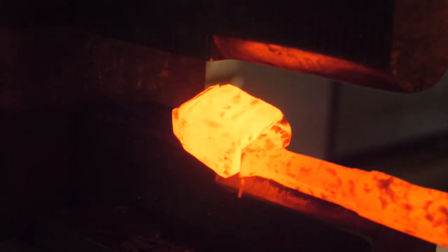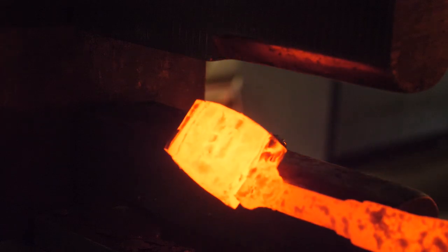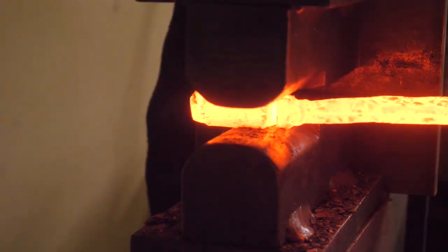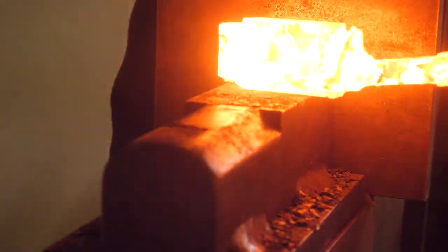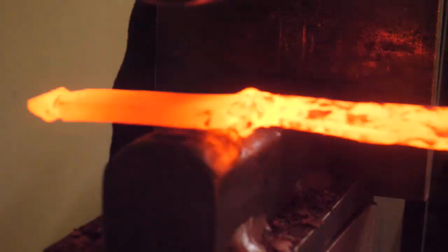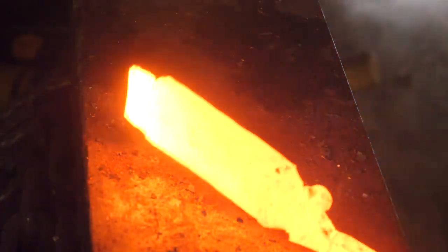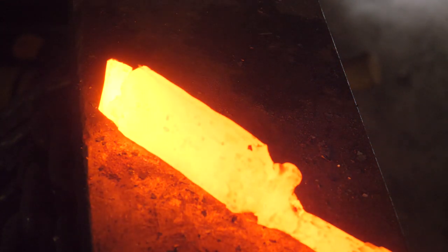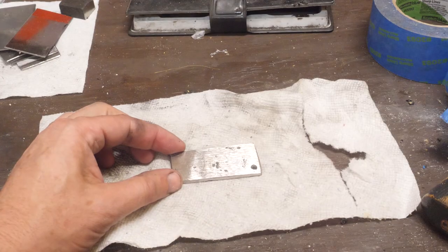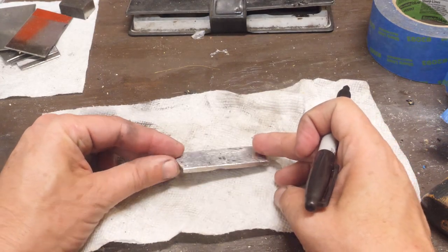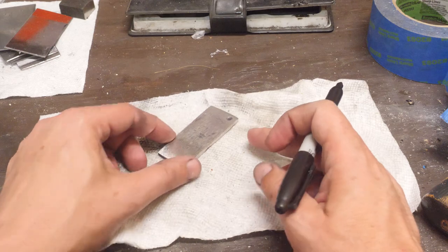I mean an A for effort, but the original welds just aren't holding up. They're just not solid enough to keep the stainless in place. I was hoping the layer of nickel would help that, but it just didn't work for me. So that's okay. Same as last time, after forging it out, we'll draw our lure out and go straight to drilling and grinding, which is going to be much easier in this case since we left this a flat bar instead of trying to hammer in some curvatures and rounding it out.